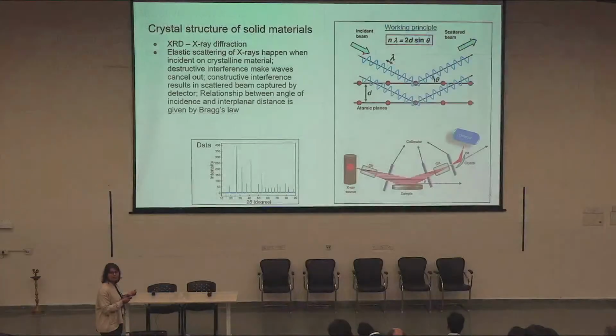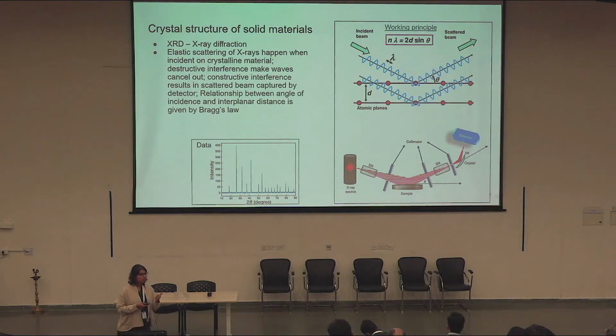But when you have a crystalline material, the order of the material will scatter the beam at the same angle theta, that is the angle of incidence of the X-rays. And all these constructively interfered scattered beams are detected by some kind of detector that you have in the system. The relationship between the angle of scattering, the incident wavelength, and the interplanar distance in the crystalline material is given by this particular equation. This equation is called Bragg's law.